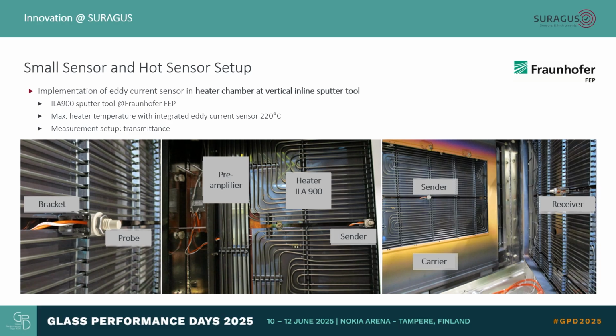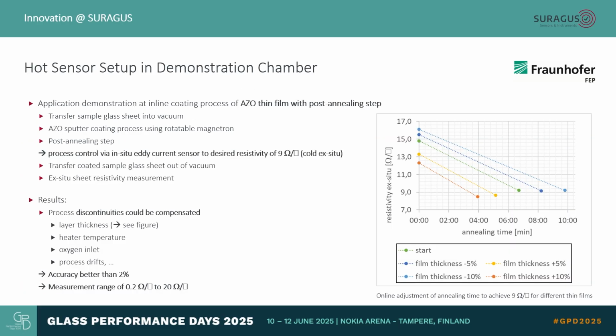So we are pushing the limits here. In this application, these measurements were used to control the tempering. So there was some AZO which was annealed for a certain time. The idea was to get it to 9 ohm per square, and we changed the annealing time and used it for quality control.